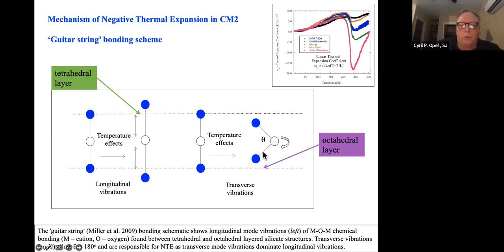So if this is a guitar string here, when you create this transverse vibration, there's a tension in this guitar string, or in this bond. And as the vibration is excited in a particular way, transverse vibrations overwhelm the longitudinal vibrations, at least at 235 Kelvin. And that's why we see this negative thermal expansion. And that's why it's so incredibly reproducible, because of the dynamic between longitudinal and transverse vibrations of the hydroxyl groups between the tetrahedral and octahedral layers.